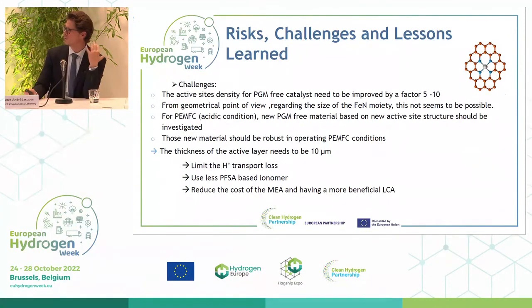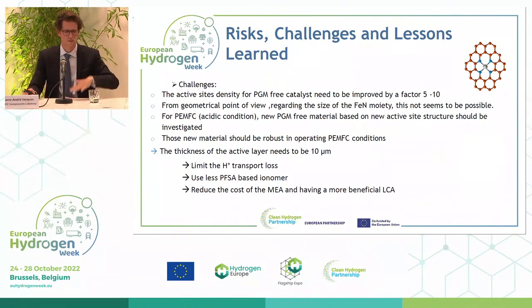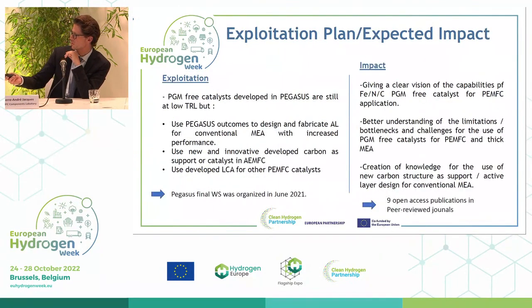And then if you want to work with PGM-free catalyst, you need to limit the proton transport loss in the active layer. So the thickness of your cathode active layer needs to be 10 microns. You need to use also less PFSA-based ionomer, otherwise the cost and the environmental cost of your material will increase. And of course, you need to reduce the cost of the MEA with the new materials.